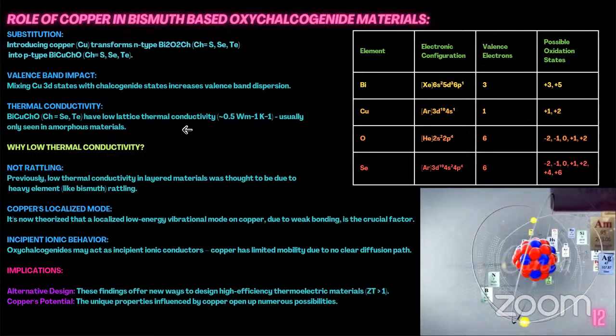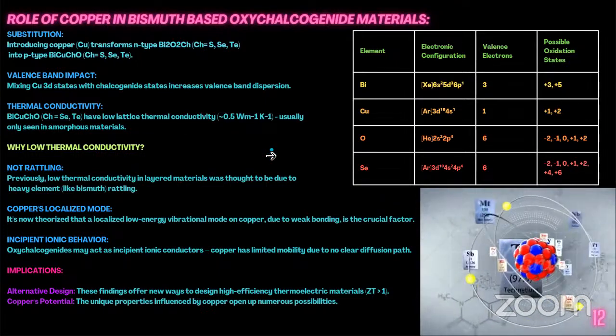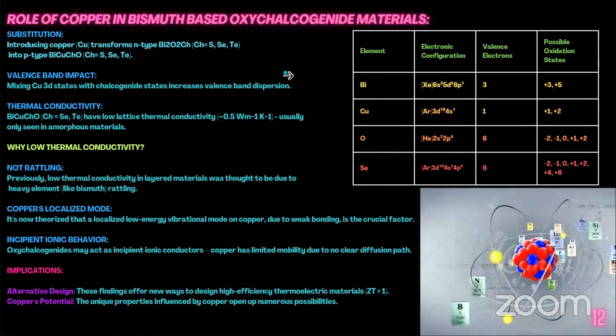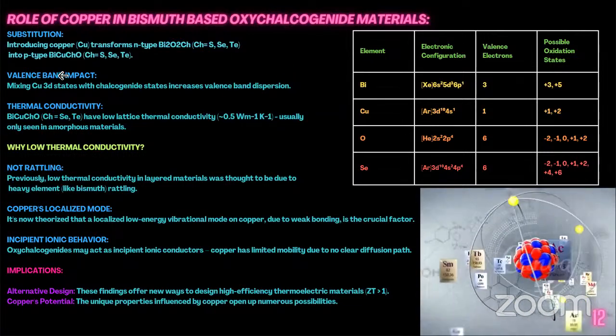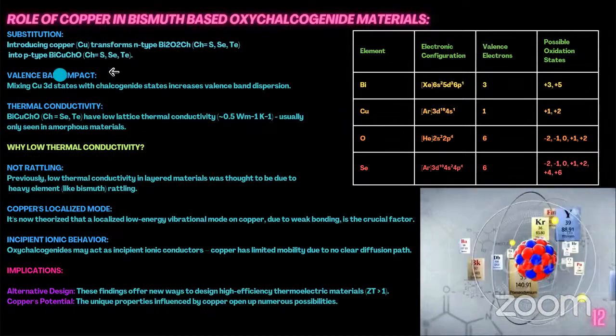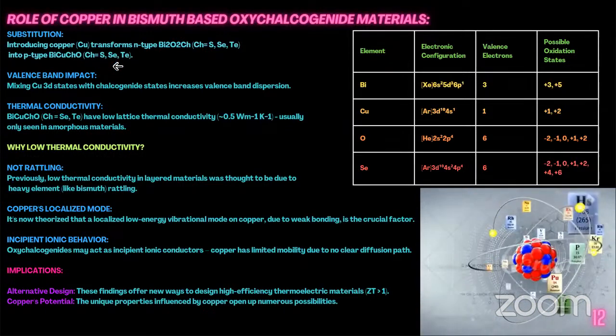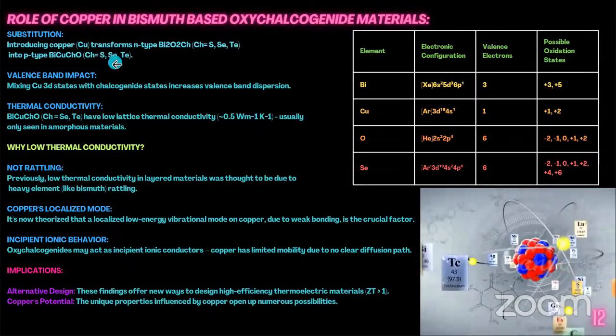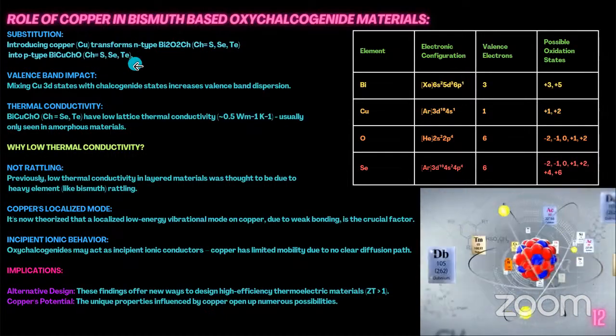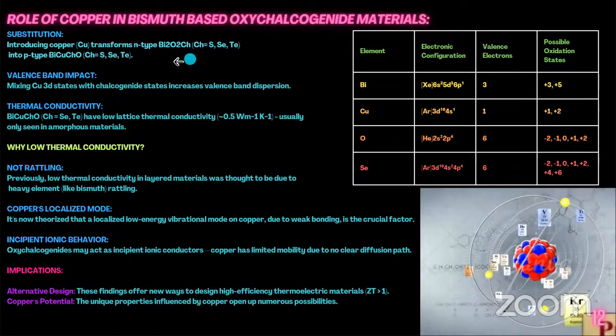Role of copper in bismuth based oxychalcogenide materials. The strategic introduction of copper atoms plays a crucial role in the materials. This substitution transforms the simpler N-type materials into desired P-type bismuth copper based oxychalcogenides. By mixing the copper's 3d states with the chalcogenide states, the dispersion in the valence band increases.